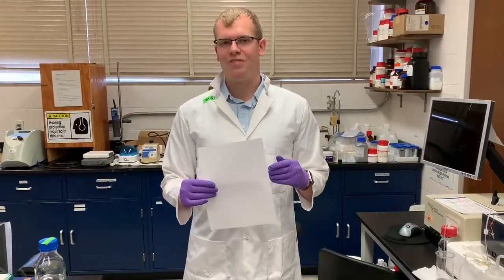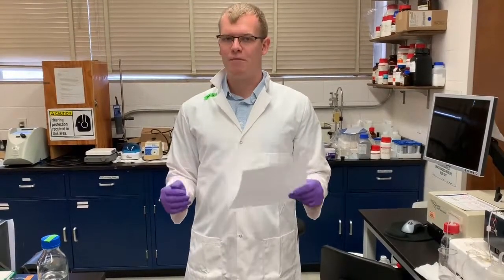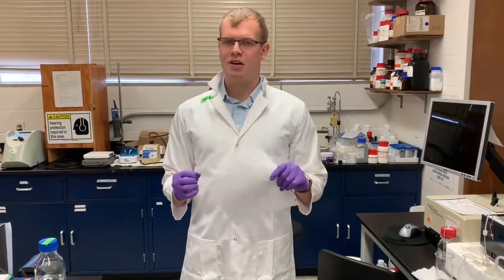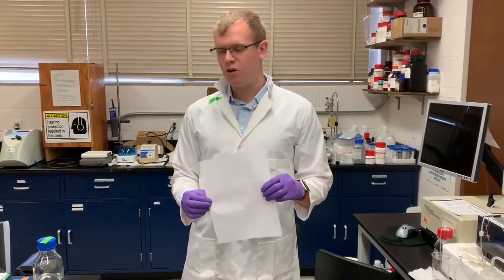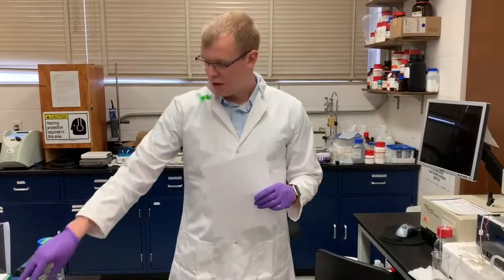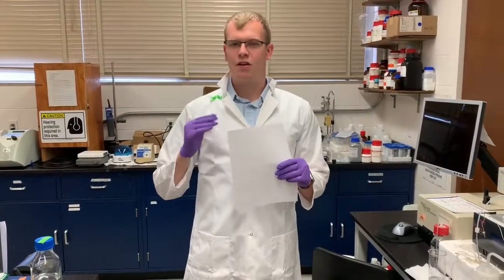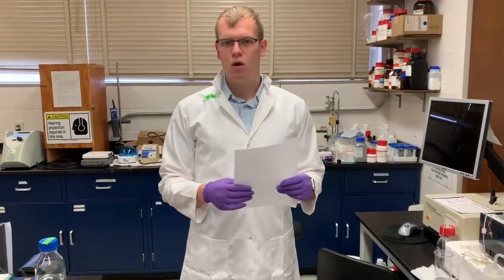But of course the issue is that the body regulates temperature very well, so you have to be careful about what temperatures you use. So what we do is we adjust the formulation of our hydrogel in order to get the transition temperature right above body temperature, and then we use a nanoparticle called single-walled carbon nanotubes, which can absorb certain wavelengths of light and then heat up. What we're essentially making here is two such samples. The carbon nanotubes act as a remote trigger for the heat response, and we can use that to remotely, from outside the body, trigger drug release inside the body, so that on demand you can release a drug.